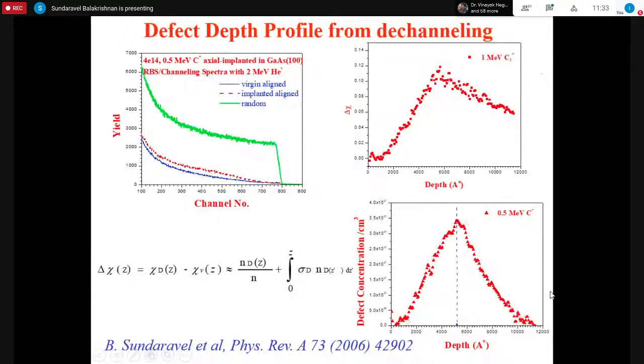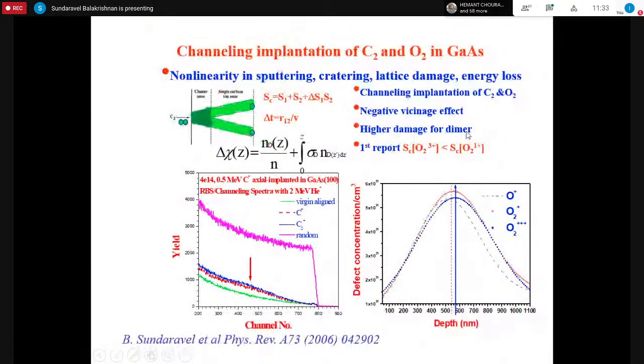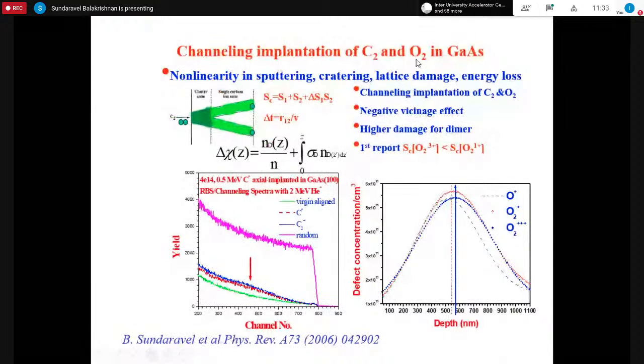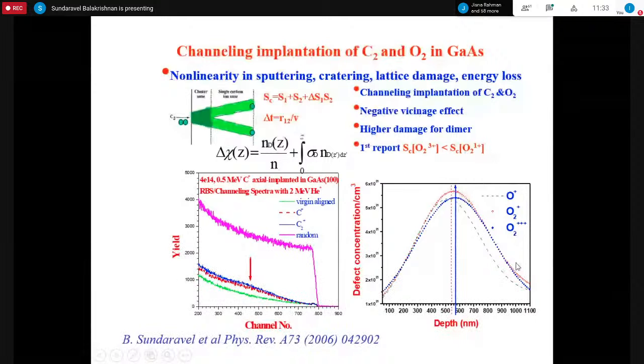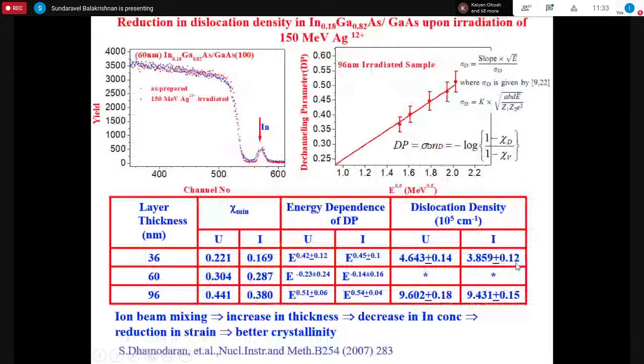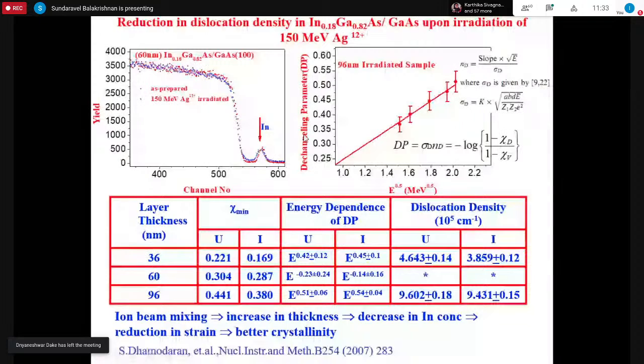And we have studied the charge state dependence of oxygen dimers. Between oxygen dimer 1+ and oxygen dimer 3+, we see that oxygen dimer 3+ penetrates deeper compared to the oxygen monomer. This we extracted from the defect profile. And here, if we take indium gallium arsenide on gallium arsenide, this is the indium signal, and this one is gallium arsenide.